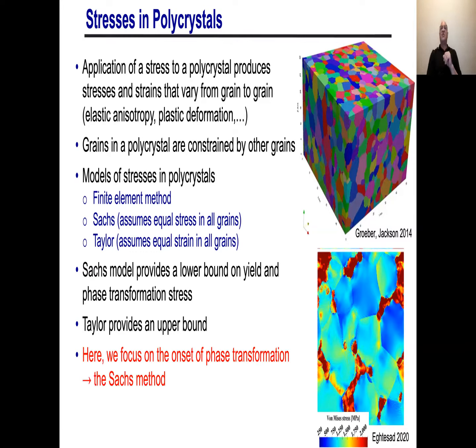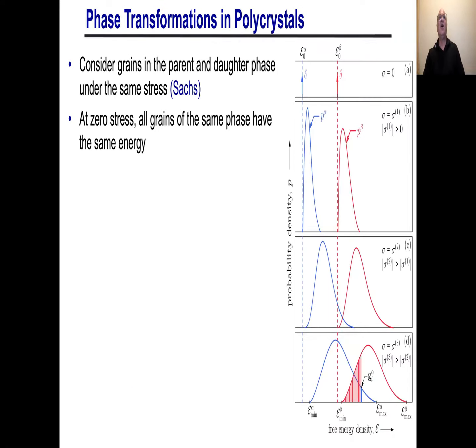So what we're most interested in is the onset of the phase transformation. So we're interested more in the lower bound. So we're going to use the Sachs approach. Okay, it's an assumption, by the way. You can do better if you really want to do the finite element calculation, but then it makes the DFT calculations too hard. So you can judge for yourself how well this works in a few minutes when I show you the results.